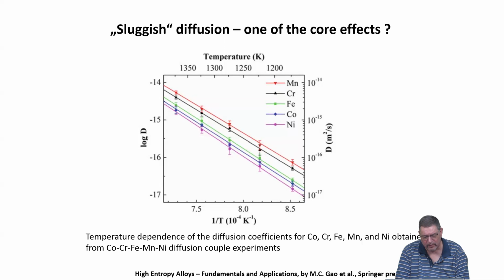Now, when you look at this, you will not see any sluggish diffusion, because it's a comparison of the different constituent diffusivities as a function of temperature in the Cantor high entropy alloy. So equimolar 5-component high entropy alloy, single phase solid solution. Why do you not see sluggish diffusion? Because sluggish could only be meant as a comment which is done in comparison to what? So sluggish compared to what, right? And I will show you later that this is not so easy to define.